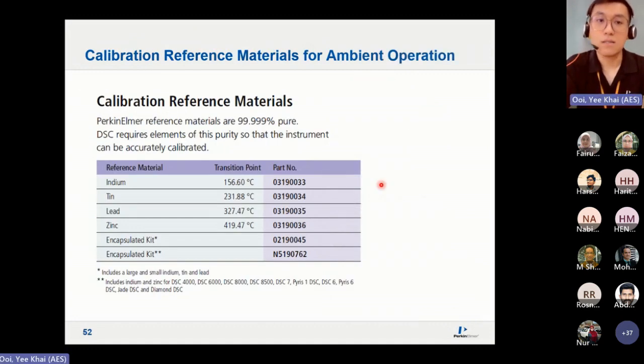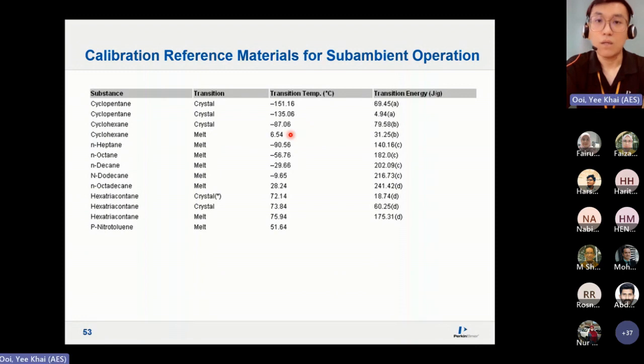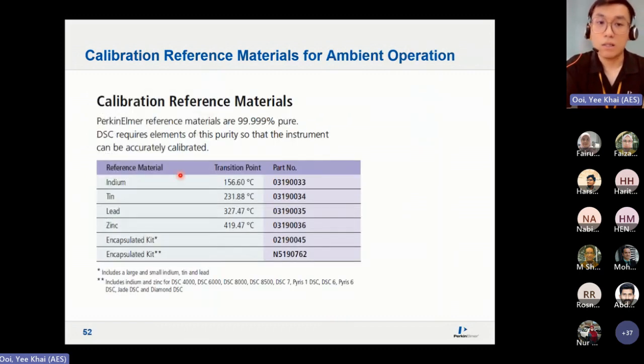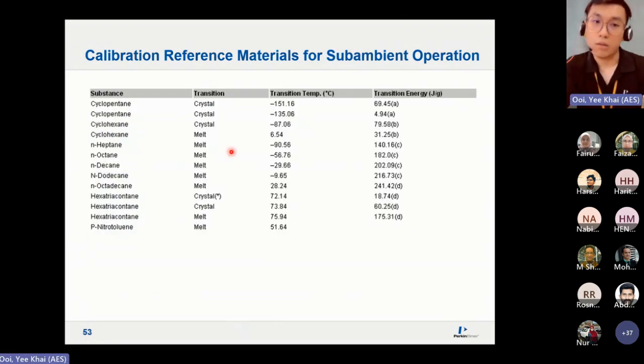So for DSC, this is the calibration material that we use to calibrate the instruments. So these are the transition points. Okay. So if you run a lot of sub-ambient analysis and you want to calibrate your instrument at sub-ambient temperature, these are the substances or reference materials with known transition points at much lower, sub-ambient temperature, as you can see from here. Because like just now, indium is 100 and above, right? 156.6. So let's say you are running your material at a way lower temperature, then these are the things that you can consider to calibrate your instruments.